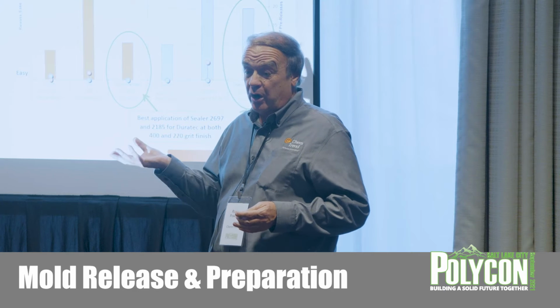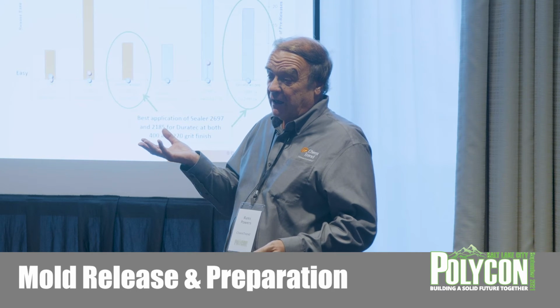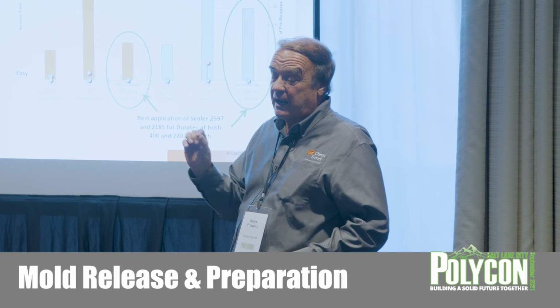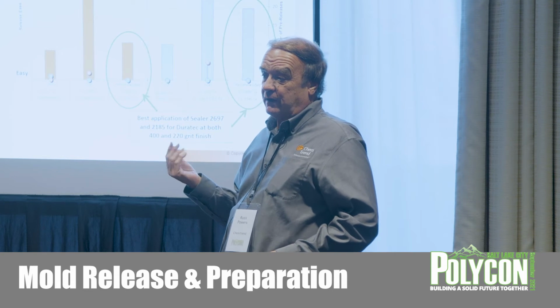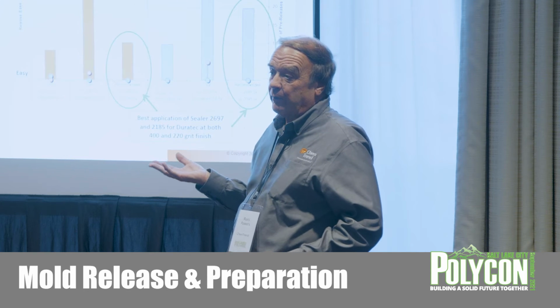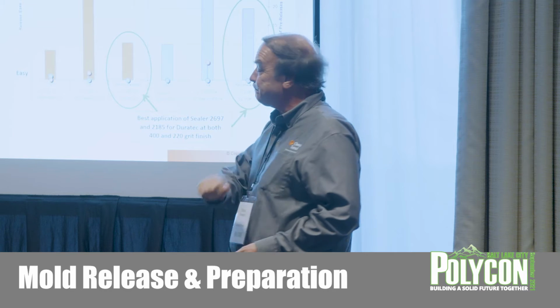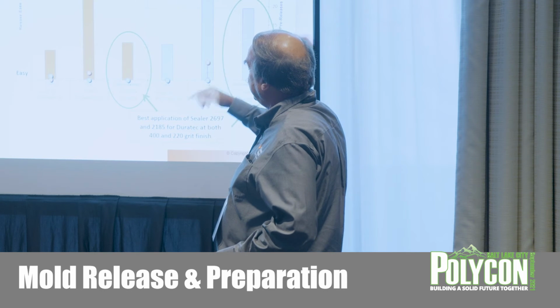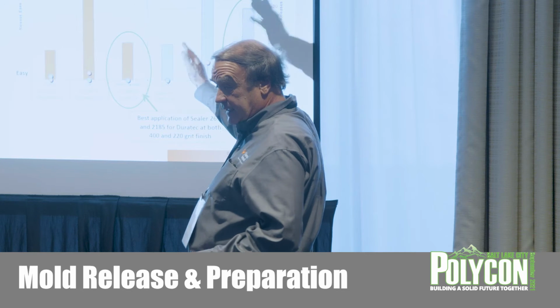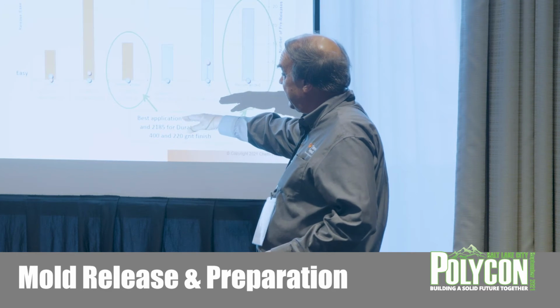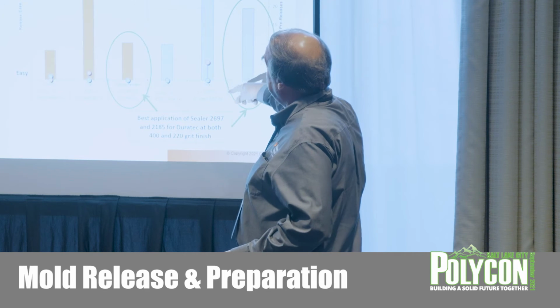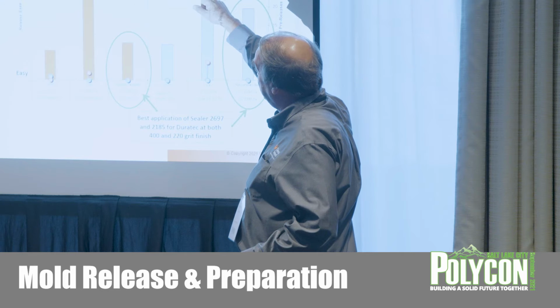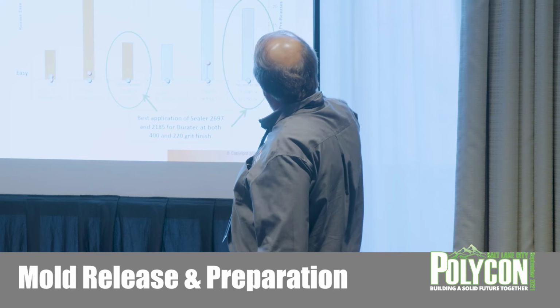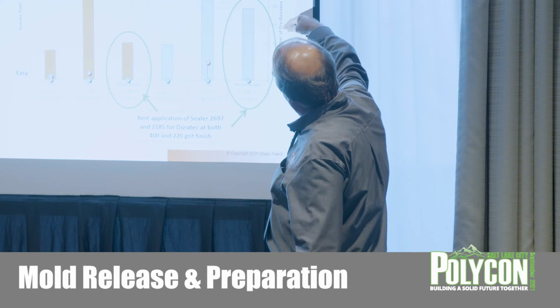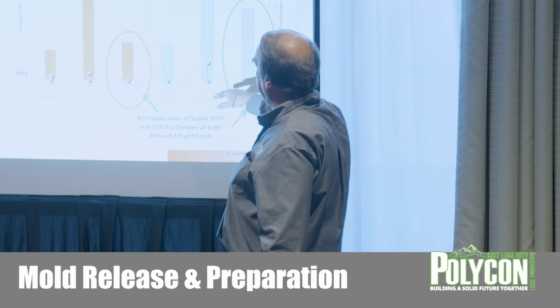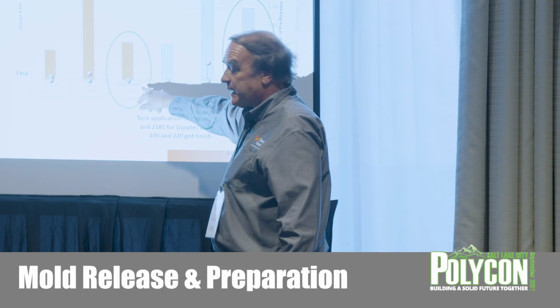Most sealers, because they're heavier solids than a standard release, because of that heavier solids, it makes them harder to wipe on and leave on without buffing, because they used to streak more. But now we have a sealer that you just wipe on. And then the third system was 2697 sealer, same sealer, and the 2185. And you have blue dots are pre-release, and pink dots are tight. And then number of issues of tight releases would apply as opposed to pre-release. And it shows that this is the best system.